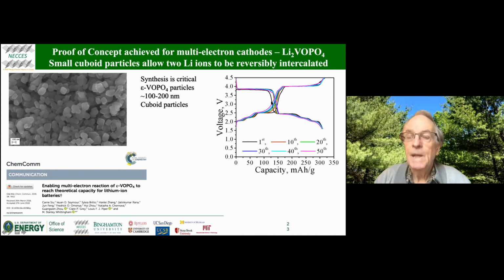You'll see the black here is the first cycle, the purple is the 50th cycle, and you can see there's essentially no change whatsoever in the behavior here. So there's no capacity loss. This is really proof of concept that a crystalline lattice can tolerate 2 lithiums going in and out without damaging the lattice. We have shown, using a related vanadium phosphate structure, we can also cycle 2 sodiums in and out of the lattice. We cannot cycle magnesium in this lattice because the magnesium, in fact, on the first discharge, abstracts oxygen, forming magnesium oxide.